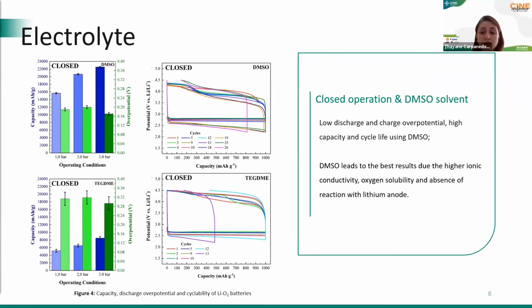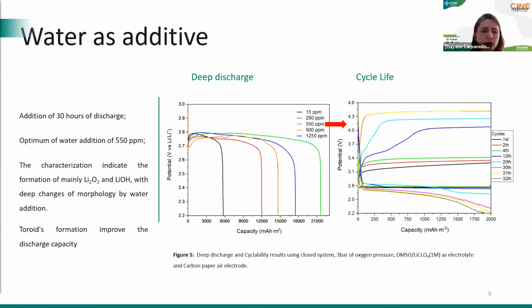And DMSO leads to the best results due to the higher ionic conductivity, oxygen solubility, in addition to the absence of reaction with the lithium anode compared with the other solvent. And using all this optimization of operation condition, we verified in a study adding water as additive how we could get nearer to practical applications.